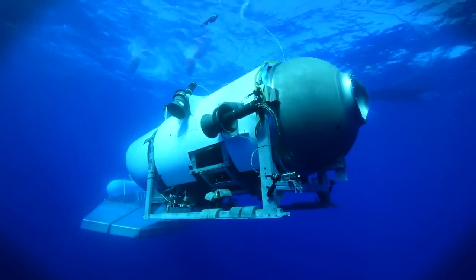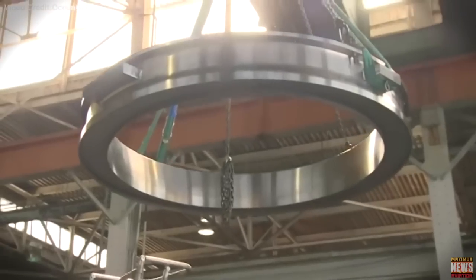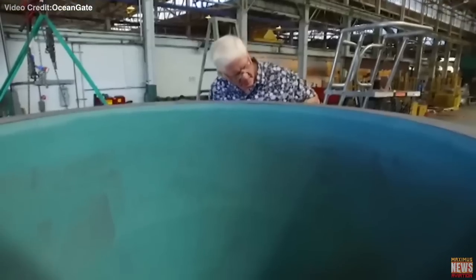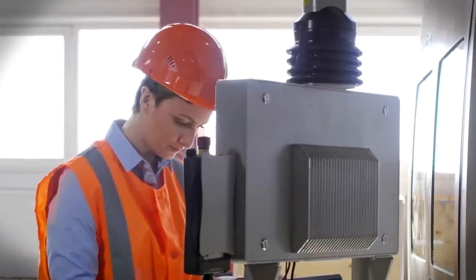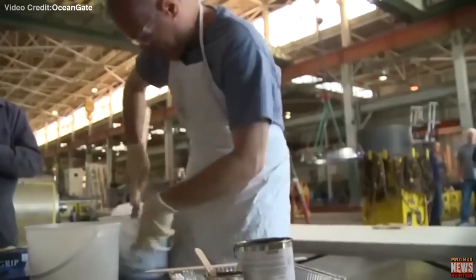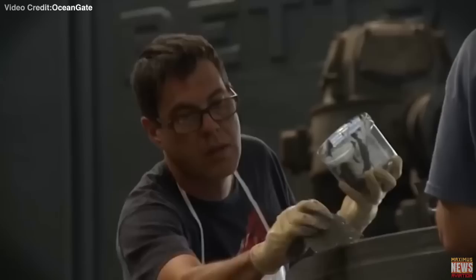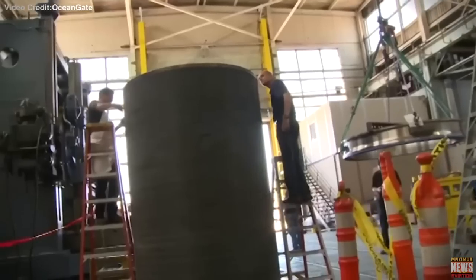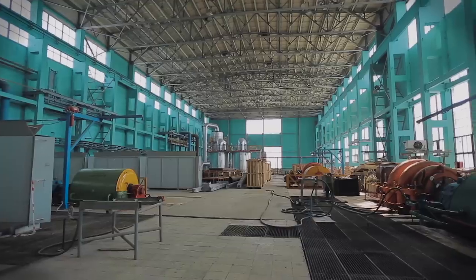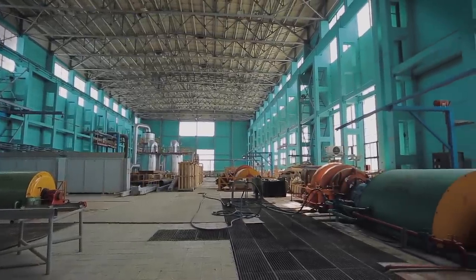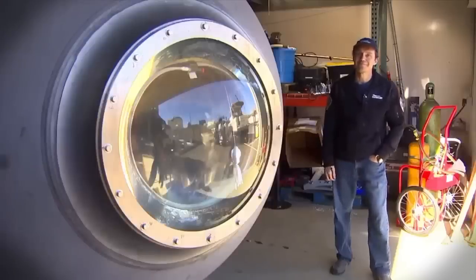It appears that Oceangate primarily relied on computer modeling without conducting comprehensive physical testing for the Titan submersible. This approach raises concerns, particularly regarding the composite hull's curing process. Without utilizing an autoclave, a pressurized oven that helps eliminate voids in the epoxy resin, there may be a higher likelihood of porosity and defects in the hull. Spencer Composites, the manufacturer responsible for the hull, claimed that the assessed porosity level was less than 1%. However, the lack of specific information about the actual porosity level leaves room for doubt.